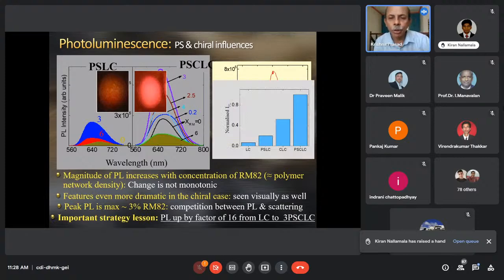The analysis of these I don't have time to go through, but probably I'll switch over to something else. You can also electrically switch these systems, and you see that when you have only the liquid crystal, there is hardly any change between the field on and the field off states. Whereas when you have only the polymer network or the chiral material incorporated in the system, there is a little bit of change, or what we call photoluminescence anisotropy, the change between the electric field on and off states. But when you have both the chiral as well as the polymer architecture, you see that there is a large change between the field off and the field on states, and the photoluminescence anisotropy is significantly large in this system. This is new in the field of soft matter, wherein you can control, through the polymeric architecture as well as imposed chirality in the system, anisotropy in photoluminescence.